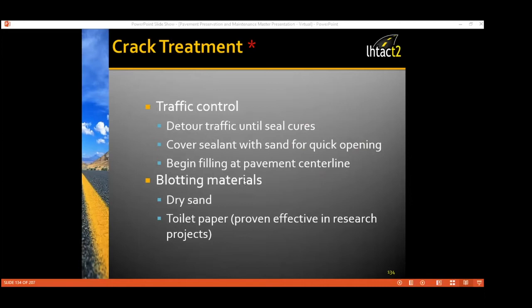So if we perform crack sealing 6 to 12 months prior to an overlay, proper sealant application procedures and roller operation techniques can eliminate those bumps caused by too much sealant being applied to the crack. And again, blotting materials, dry sand's the best. Again, somebody has tried toilet paper. The research project said it was effective. It's like, no, in my opinion, it's not.